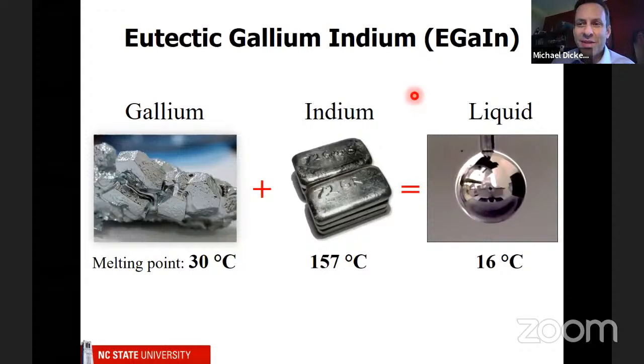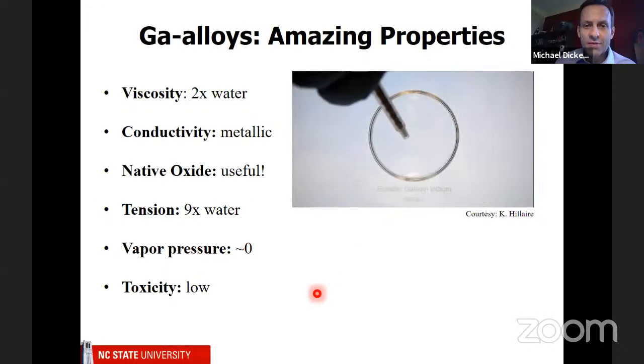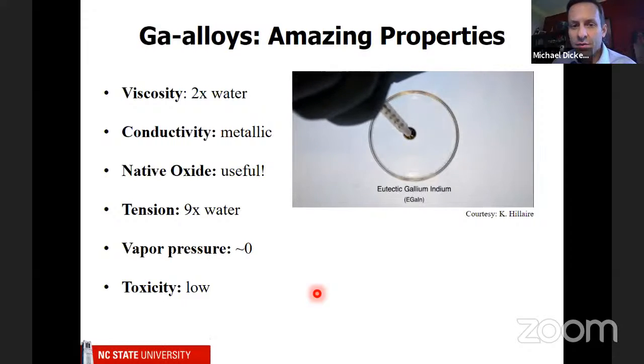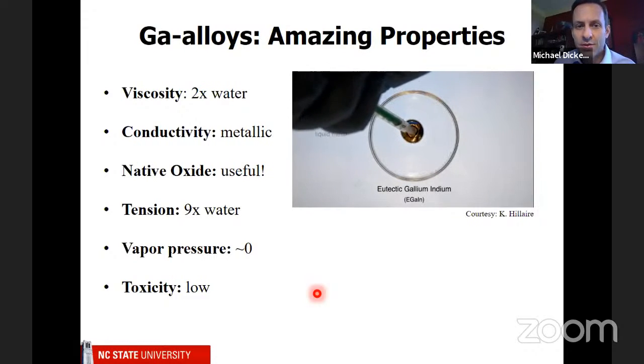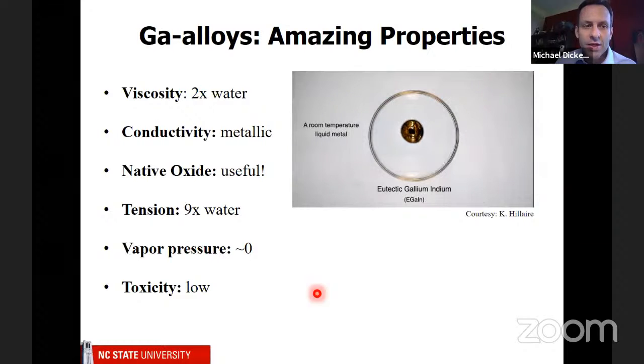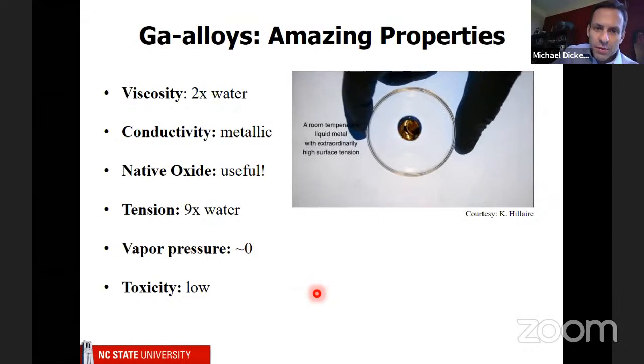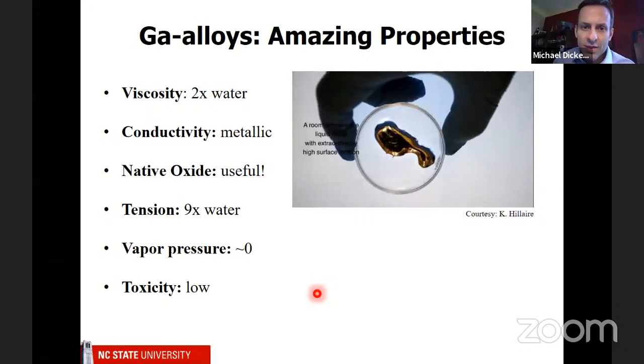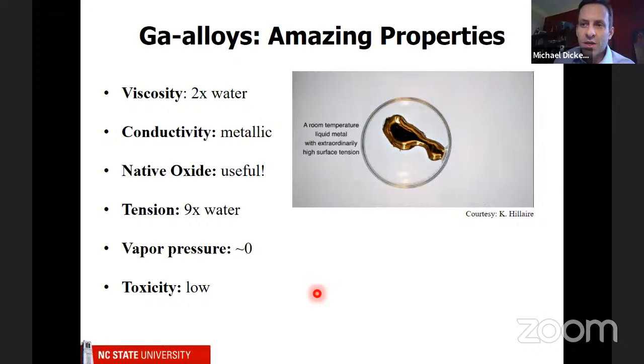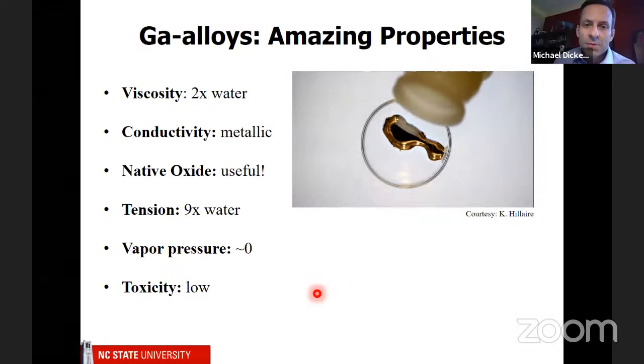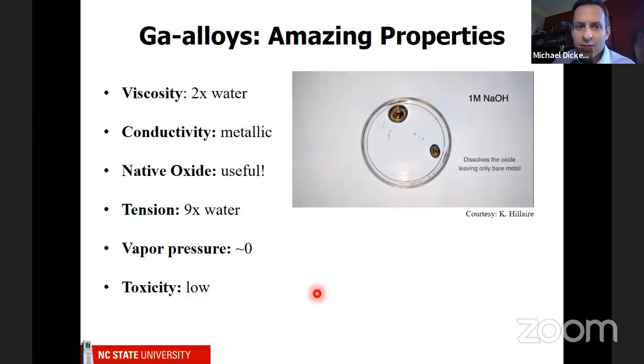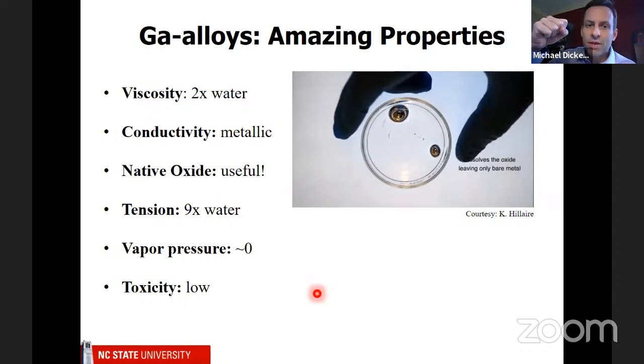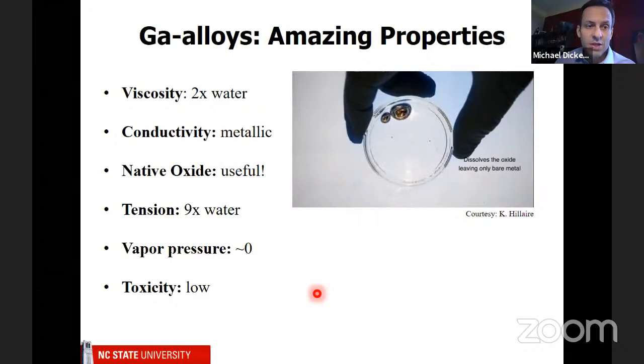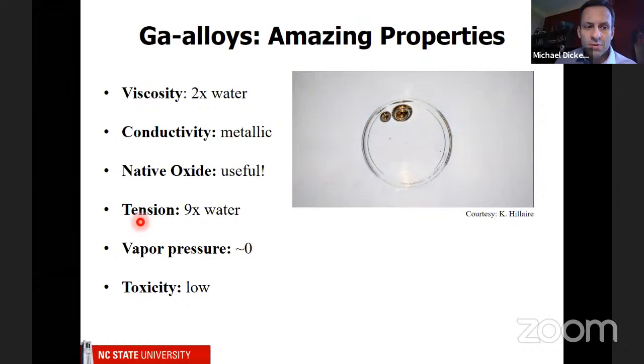Okay, so I mentioned many amazing properties. This is a video that shows that you can take the metal and squirt it out of a syringe. So it's a liquid. It's got metallic conductivity. If you swirl it around, you start to see some weird behavior. It takes on some shapes that would normally not be associated with high surface tension liquids. And that's because the surface reacts with air and forms an oxide. If you dissolve away the oxide, the metal simply beads up due to its very high surface tension. Because of the very large surface tension of the metal, it tends to form a sphere.